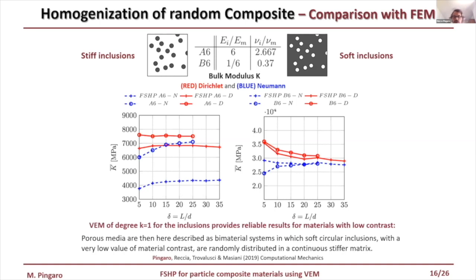This is strictly related to the high stress gradient around the inclusions. Another interesting result is the possibility to model large windows. This is, of course, related to the reduced number of degrees of freedom using the VEM methodology. This is very important because, especially for materials with very high or very low values of contrast, a large window dimension is required to reach convergence of the procedure.